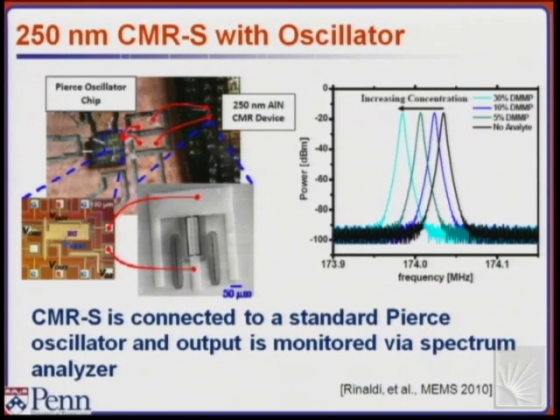What we've also done, and this is work that will be presented at MEMS 2010, is connect this resonator, the thin 250 nanometer one, to an oscillator, the same oscillator actually. It works very well, so it's interfaceable with electronic circuits. We functionalized it with DNA as well, but we did not grow nanotubes on this one. We didn't want an extra challenge. On top of that, we just used gold and attached thiolated DNA to the gold. It works as well. You probably lose a little bit of surface area, the advantage you have with the nanotubes, and we connected it to a Pierce oscillator.